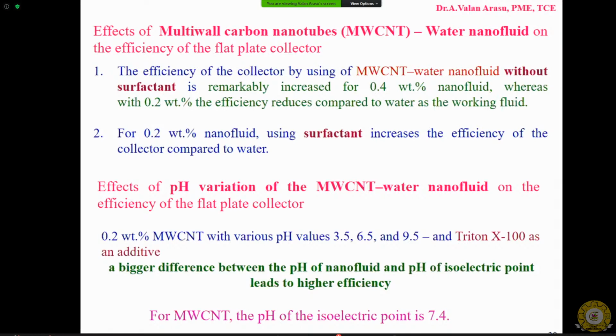So before putting these nanoparticles into use, we have to find the optimum concentration, or the most effective concentration, of nanoparticles through intensive research and extensive experiments. But for 0.2 weight percentage of nanofluid, when we use surfactant, the efficiency is increased compared to water. So it is clear that for this multi-wall carbon nanotube, when the concentration is lower, the dispersion is not uniform or stable. That is why when we use a surfactant, the suspension becomes stable, and the effective thermal conductivity as well as the heat transfer is increased, resulting in the increase in the efficiency of the collector.